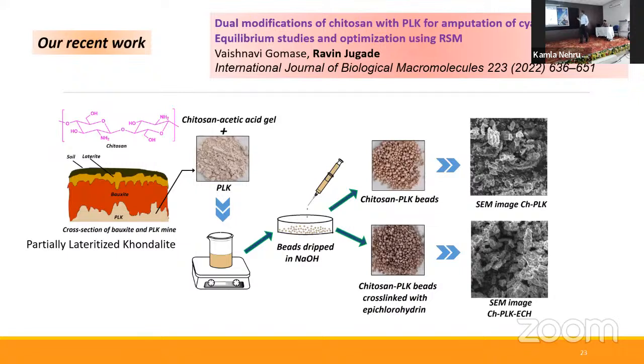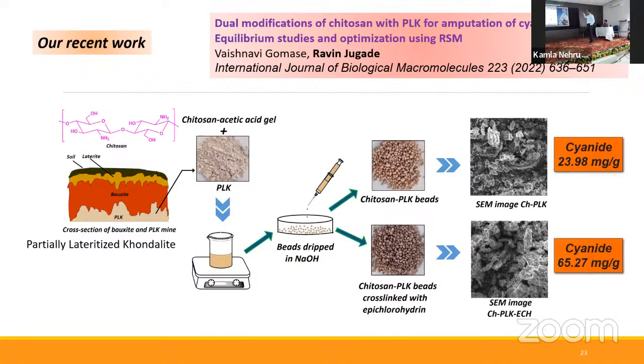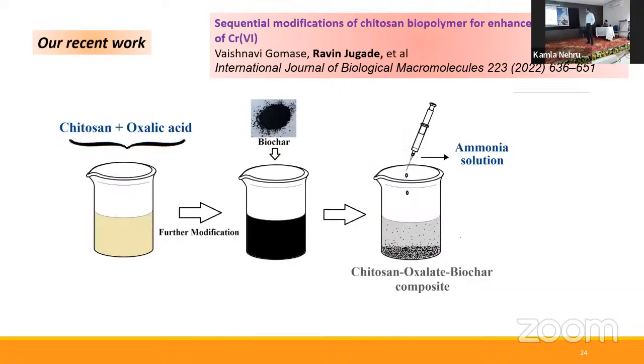And it was found that they have very good absorption tendency towards cyanide ions from water body. So 23.98 milligrams per gram and 65.27 milligrams per gram. All of these are reported and they have been published in various journals.